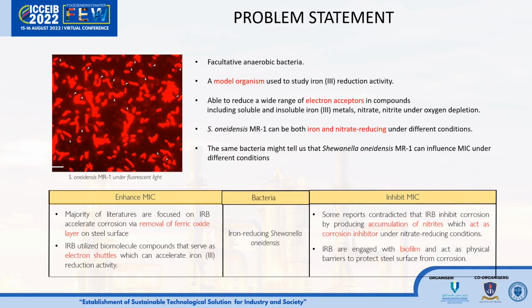Most of the literature focuses on MIC acceleration by iron-reducing bacteria, IRB, through removal of ferric oxide on the steel surface, but iron-reducing bacteria are also postulated to inhibit MIC by transforming insoluble iron 3 oxide to other iron 3 or 2 substances such as magnetite, hematite, and vivianite as a physical barrier or protective layer within the microbial biofilm formation against corrosion under anaerobic conditions. Thanks to the facultative anaerobic nature of Shewanella, due to its capability to reduce a wide range of electron acceptor compounds such as soluble and insoluble iron 3 metals, nitrate, and nitrite.